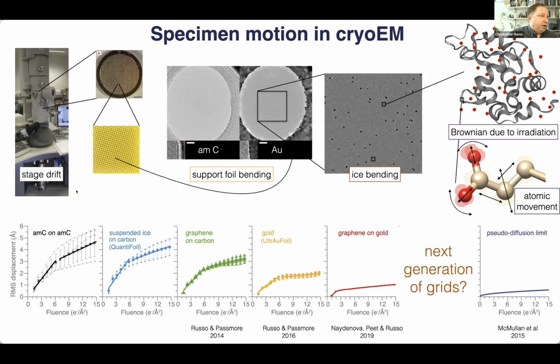So this slide is just summarizing the length scales over which specimen movement occurs. And there's the earliest or most well-recognized form of specimen drift, which is stage drift. So if you have a specimen at cryo temperatures and it's being cooled by a copper rod, and that copper rod changes in temperature by a fraction of a degree, you get tens of angstroms of change in the length of the rod, and therefore you get drift of the specimen. And so this is a boring form of drift, but it was one that was solved earliest on with careful design of the cryo specimen holders.